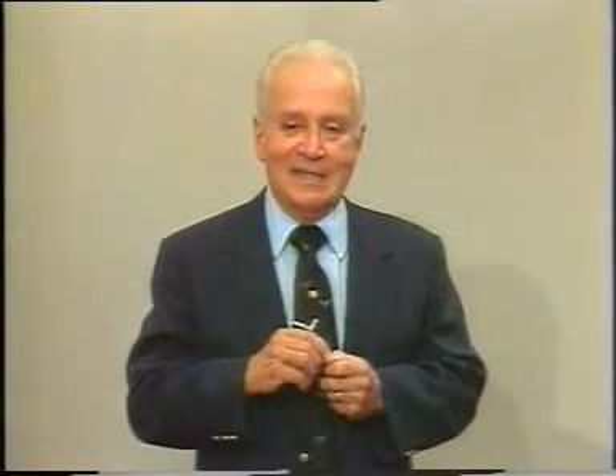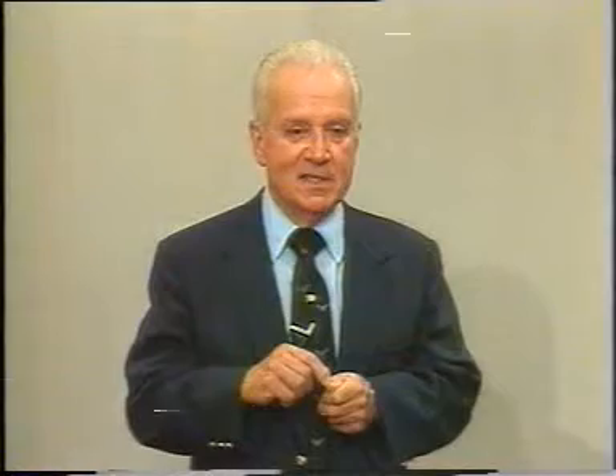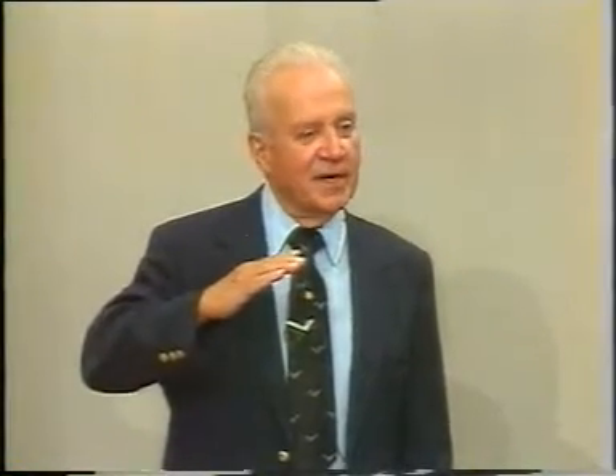You will recall that when we talked about heat treatment, we talked about the Jominy hardenability test, where we quenched one end of the material, and then we examined the hardness along the length of the bar. So we stretched out the thermal flow effect, so to speak, or the heat treatment effect. When we want to look at the hardness under the surface of the material, we have a little bit of a problem. So we have to cut the material at a very shallow angle so that we can detect the hardness at the very surface, a fraction of a millimeter below the surface, and a fraction of a millimeter below that.